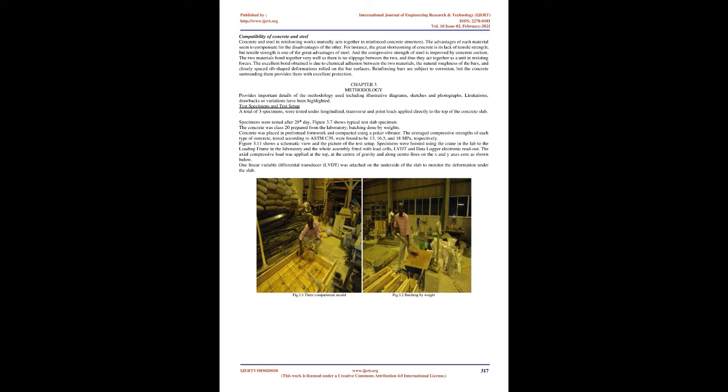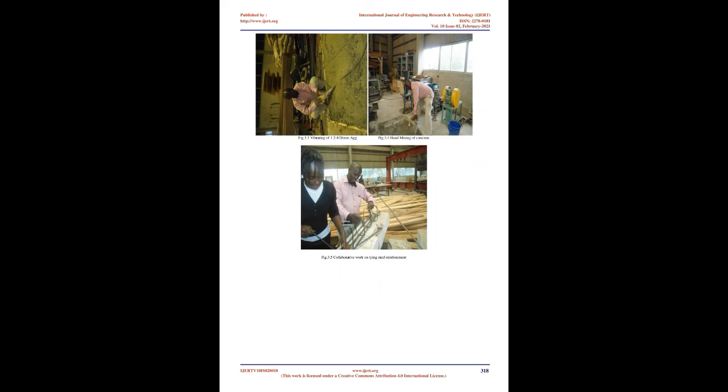Chlorides. Chlorides, including sodium chloride, can promote the corrosion of embedded steel rebar if present in sufficiently high concentration. Chloride anions induce both localized corrosion, pitting corrosion, and generalized corrosion of steel reinforcements. For this reason, one should only use fresh raw water or potable water for mixing concrete, ensure that the coarse and fine aggregates do not contain chlorides, and not use admixtures that contain chlorides.